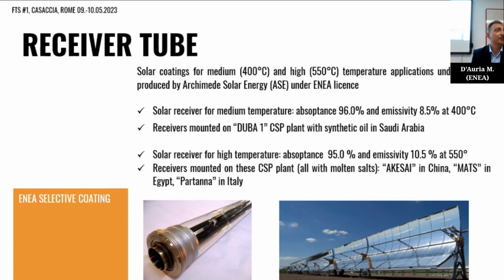Okay, Marco, sorry, we have a question from a remote attendee. Benedetto asks if there is any inconvenience in using dual heating systems for salts at temperatures below 300 Celsius degrees, for example for unfreezing the solar salt. I don't think so, because the frozen solar salt can be dielectric, so we have no issues in this way, but.